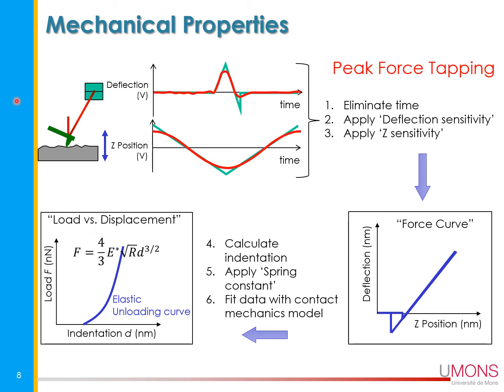So now, if you want to do that, because for one pixel of this image it takes approximately 1 second, which means that if you want to generate a 512 by 512 pixel image, you need almost 3 days to do so. So the idea is to work faster, and thanks to peak force tapping, you can proceed to one force curve with a frequency of 1 or 2 kilohertz, which is 1,000 times or 2,000 times faster. And out of that, we can generate the force curve. And this is what we observe here.